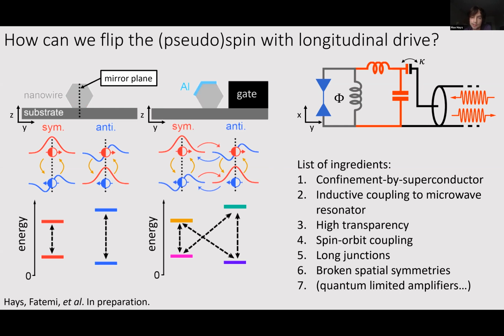In our system, though, this mirror symmetry is not necessarily given at all. In fact, just by the design of the device, we don't expect this mirror symmetry to exist. The aluminum is going to be only on two facets of the nanowire, so this is automatically breaking the mirror symmetry that we had before. Then we also have a side gate. So in principle, this is all going to be mixed up, and this allows us to drive transitions with spin flipping and spin conserving between the two doublets.